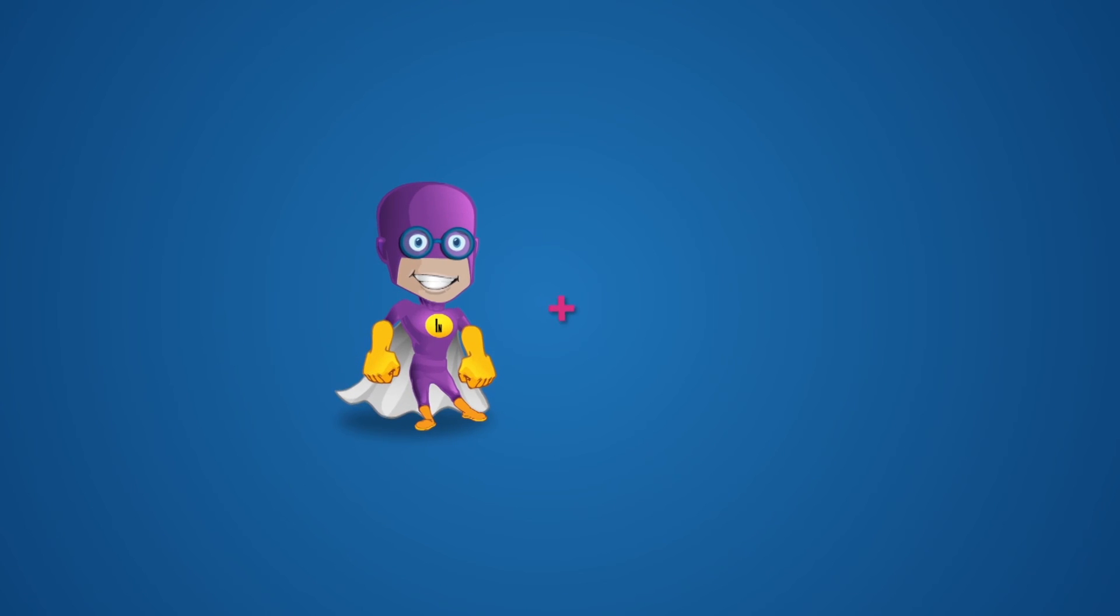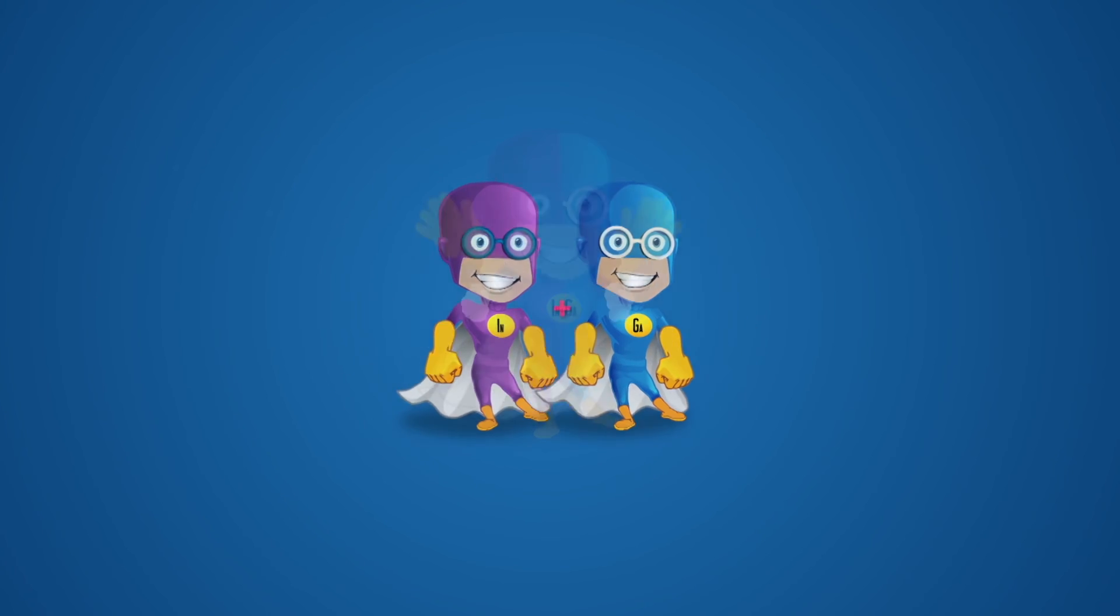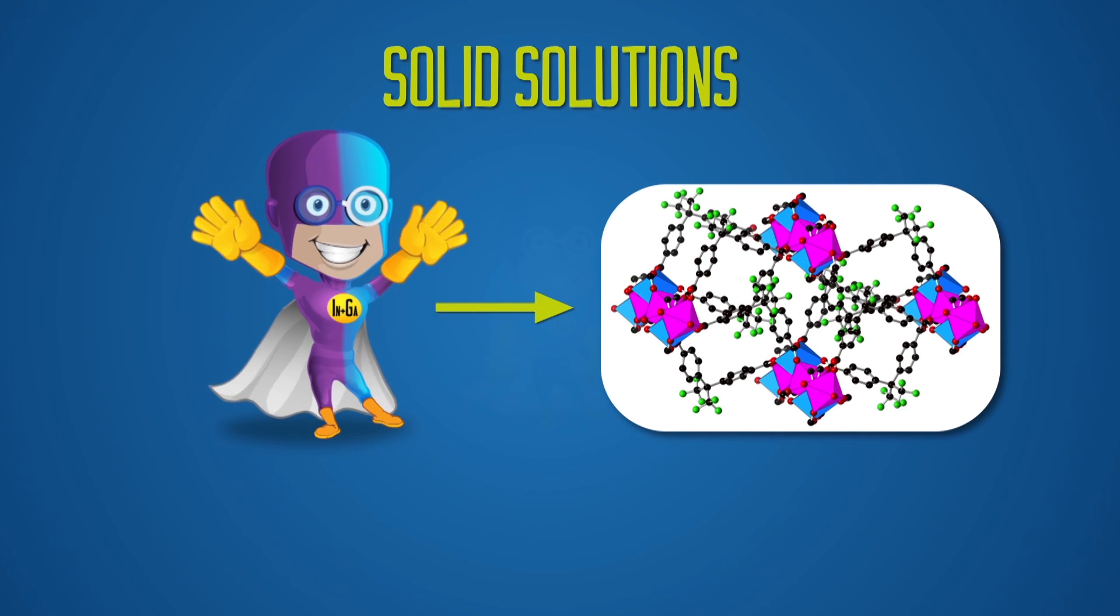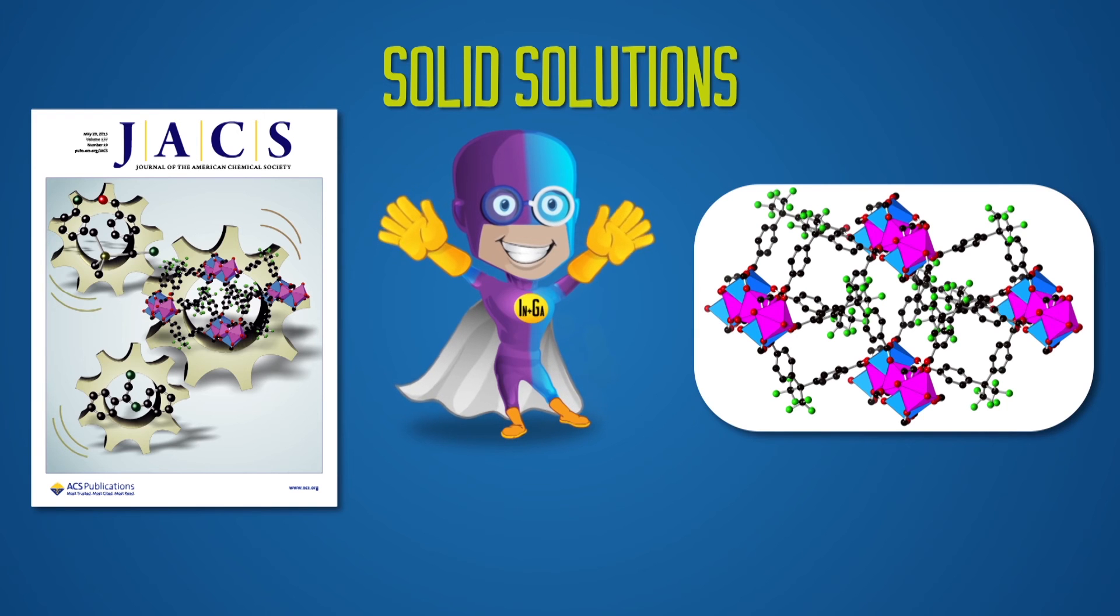So, a complete study of this behavior allowed us to redirect the catalytic selectivity by using physical mixtures of two different MOFs, and also to develop the first reported bimetallic MOF solid solutions containing indium and gallium in the same crystallographic framework position.